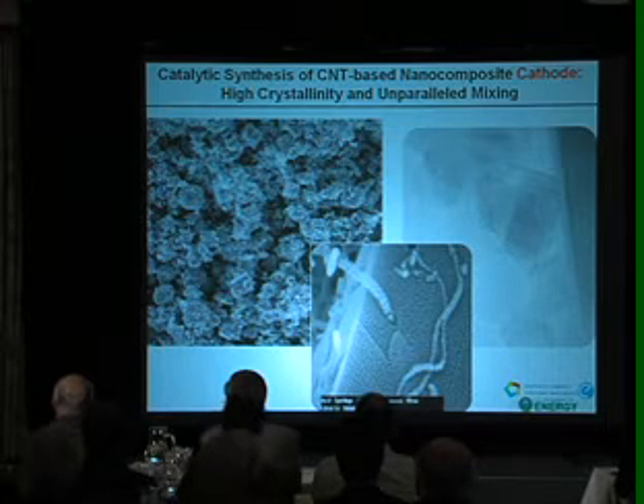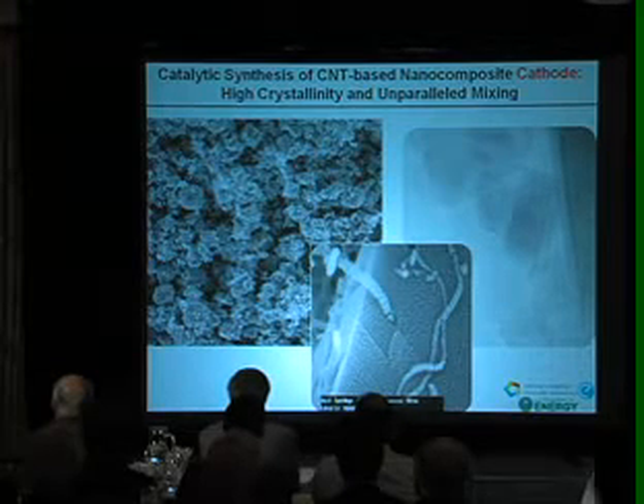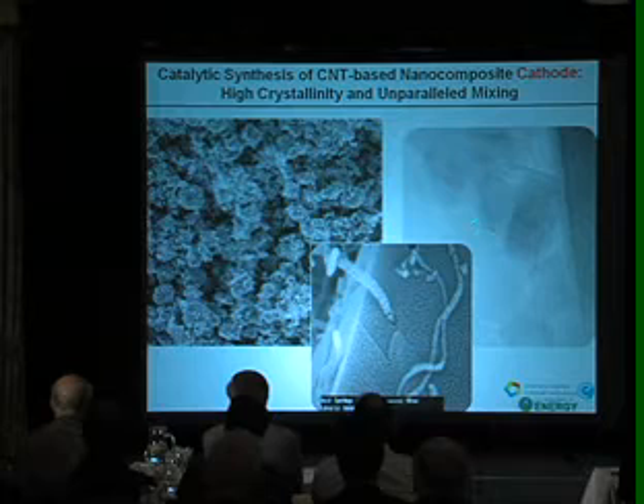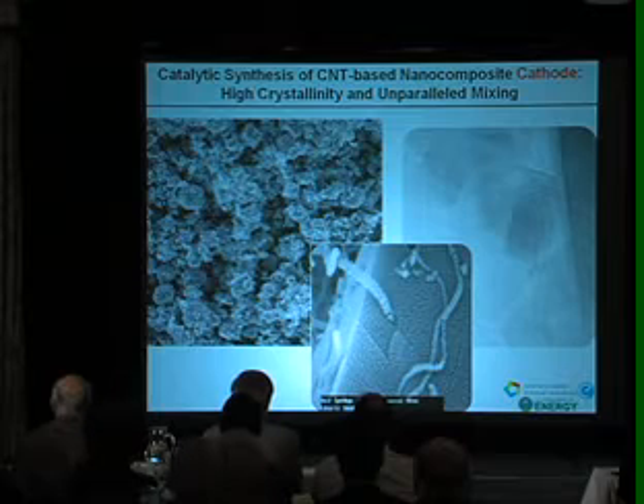Because we're growing the crystalline metal oxide in situ in the matrix of these carbon nanotubes, the marriage between these materials is truly intimate. Here you can see that the nanocrystal has formed around the carbon nanotubes in some cases. And this high-resolution transmission electron micrograph confirms the uniformly high crystallinity of this material, confirming our X-ray diffraction results.